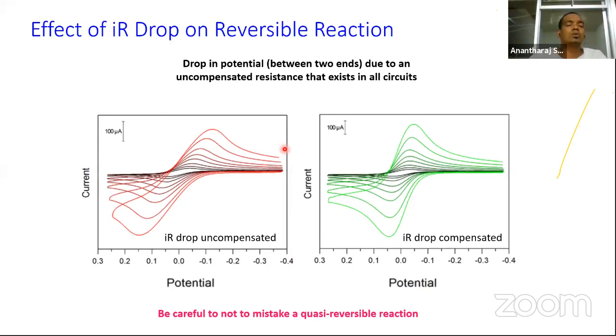Now we are going to talk about the effect of IR drop on a reversible reaction, which is controlled by diffusion. We know what IR drop is, because I have told that every electric circuit, DC or AC, has its own intrinsic resistance, which causes a drop in potential between 2 points. The 2 points I'm talking about here are always the electrode surface and the electroactive species in the solution. So as a result, when you increase the potential, even though the reaction is completely reversible in terms of both chemical and electrochemical nature, you will see a shift in potential towards the higher overpotential region with increasing scan rate.